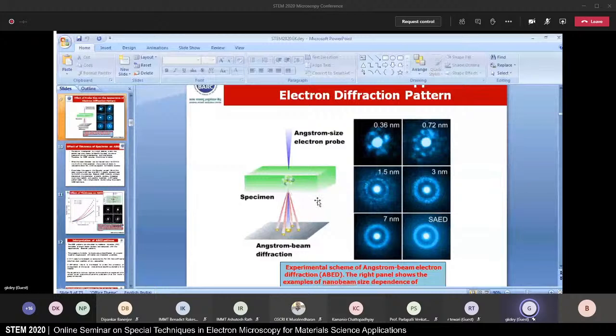What you see is a selected area electron diffraction pattern, which we are all familiar with, taken from an amorphous material. Are you seeing this slide? Yes. If you start making the beam smaller, you can see the change in the appearance of the diffraction pattern. From a ring pattern, slowly it becomes a spot pattern. And finally, when the beam is of the size of 3 to 4 angstrom, you start getting spot patterns. Remember, this is not a crystalline material. This is an amorphous material, but still you are getting spot patterns.